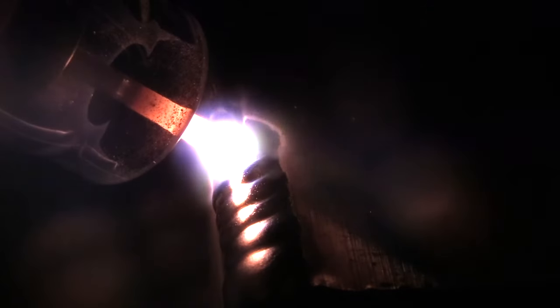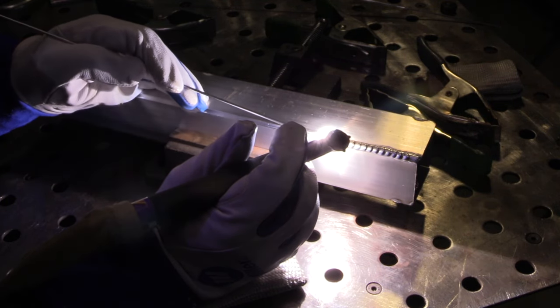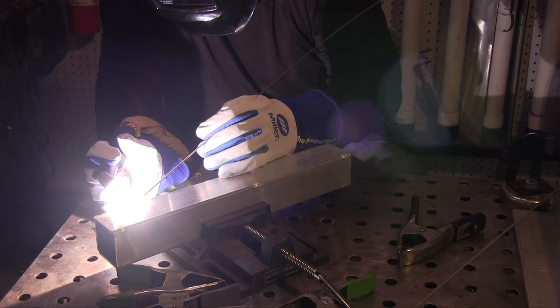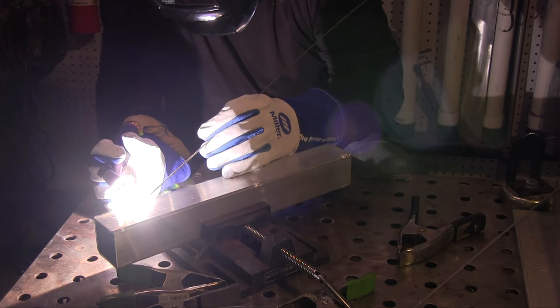You saw right there I put a tack weld about a half inch inboard and then I backed up and welded over top of the tack. That's just a habit to prevent from melting a tack that might be under strain that might pop loose and leave a gap. Not a bad little technique to use sometimes.